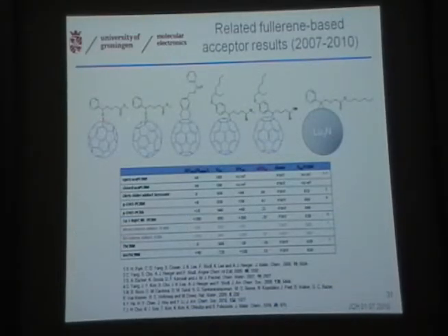So in the literature, if we look further, these two look very much like PCBM, but there's a nitrogen atom there. It's a typical Fred Wudl trick to make an alternative. He has the 5,6 and the 6,6 azafulleroid, and fulleroaziridine, I think, compounds. And then the Fréchet Diels-Alder adduct. Here you see two other Wudl derivatives with the solubilizing chain. And here we have the endohedral material that was popular a year ago, I think. We looked at the whole set of delta-delta VOC, and it's roughly all within experimental error. There are no surprises there.